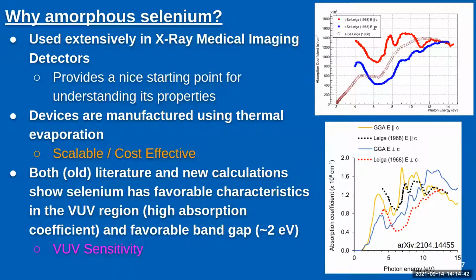Both, I would say, relatively old literature and some new calculations we've done with various condensed matter colleagues show that selenium has favorable characteristics in the VUV region, that of a high absorption coefficient and a favorable band gap around 2 eV. The plot on the top is data taken back in the late 60s, which shows the absorption coefficient as measured in the range of VUV photons for both crystalline selenium, trigonal selenium, and amorphous selenium, which are very similar to one another. The plot on the bottom is a reproduction of that data with some first principle calculations done using density functional theory, along with collaborators here at UTA.